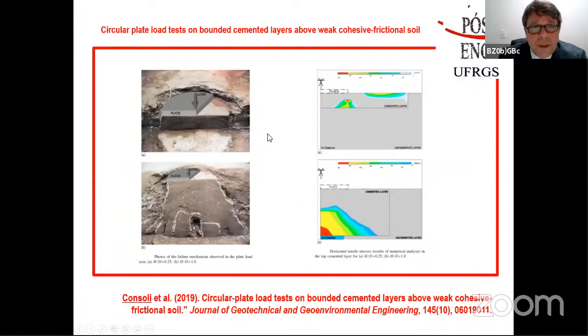Here is a paper in which we have also improved the layer in the field, and we have seen the failure mechanisms as a function of the thickness of this layer. We have done it in the field, and we also carried out some numerical analysis showing how the situation started with tensile strengths.